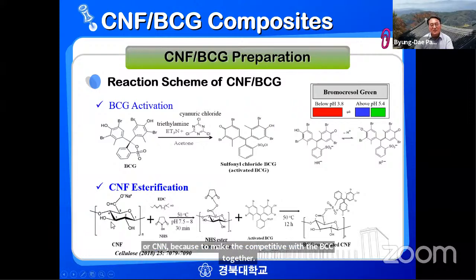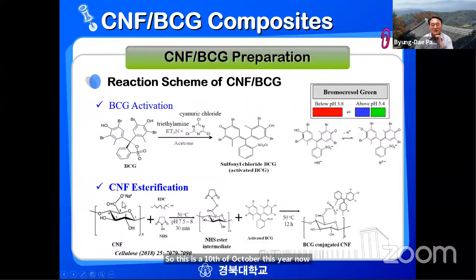So this is a TEMPO-oxidized CNF. They have the sodium carboxylate on the surface, which is negatively charged, and then we use EDC, NHS, and proper reaction conditions, and then we have the intermediate product. This intermediate product reacted with activated BCG to make the BCG-conjugated CNF like this.